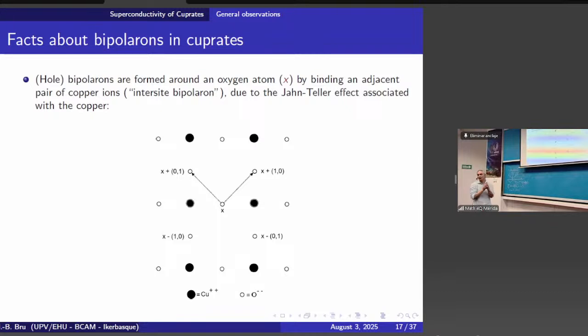So now I speak about bipolaron. It's antiferromagnetic. So the polaron, when you have it, it's favorable to have two holes which are trapped at the same time, making not a polaron but a bipolaron. So there is a geometric deformation here, a polaron here and a polaron here, and they are connected via the oxygen. And this is favorable because you can add this with a spin up and then a spin down, and it is shown experimentally that even beyond, with doping, there is antiferromagnetic correlation.